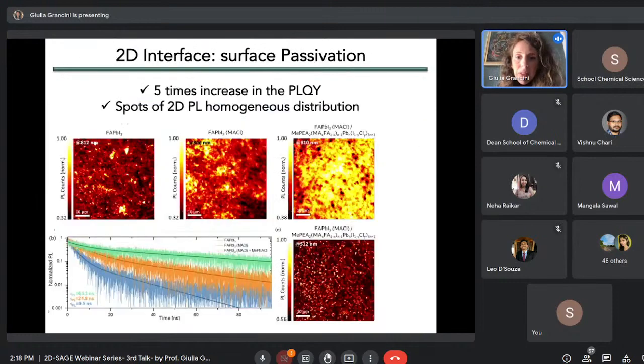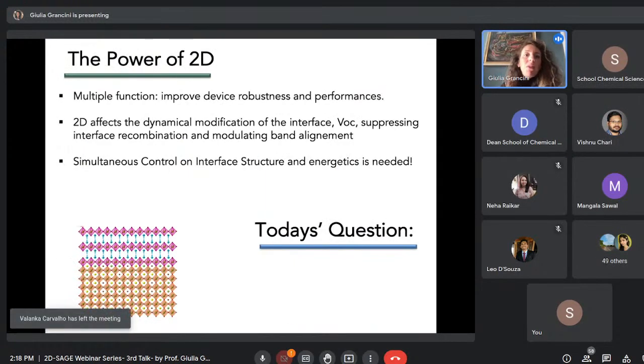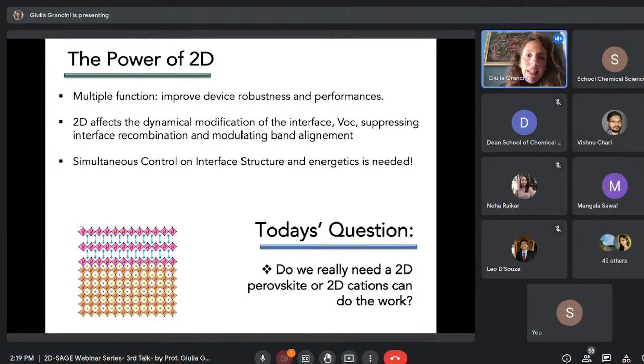This is very important because it is an essential element of the added function of the 2D perovskite on top of the 3D. So what's the power of the 2D? Improve device robustness, but also performances, affecting the interface, suppressing interface recombination. But it's very important to simultaneously control the interface structure and properties. But the question today is, do we really need a full 2D perovskite, or can just surface passivation do the same work?